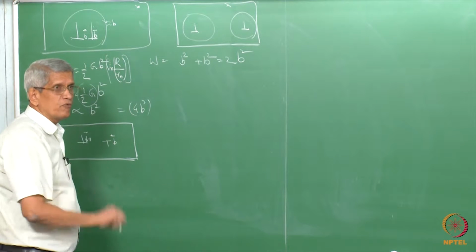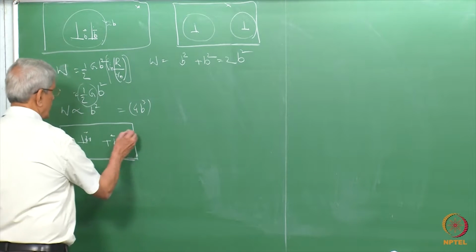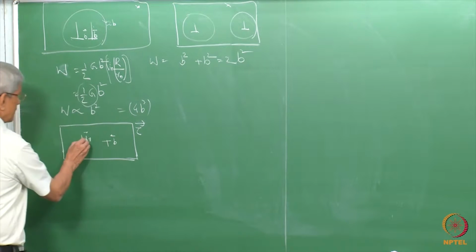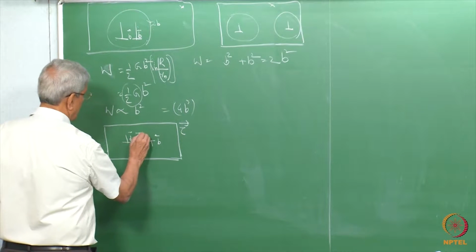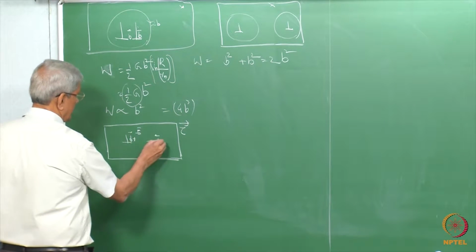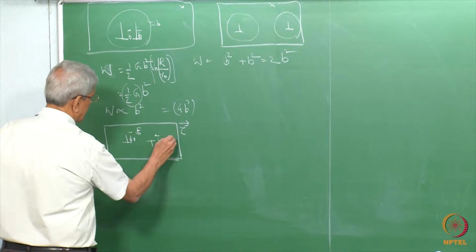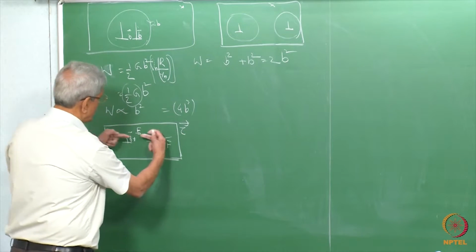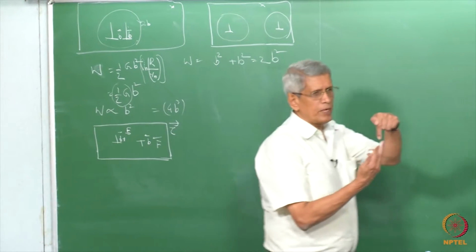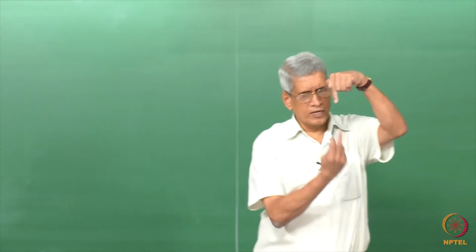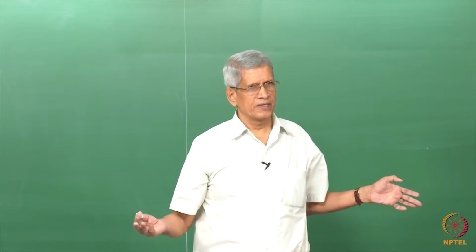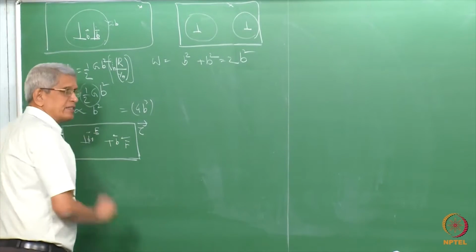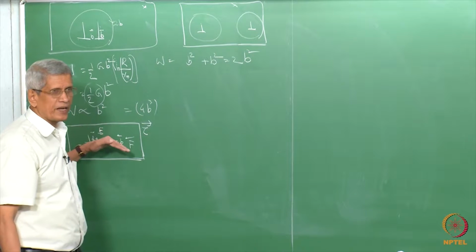If we use the force equation which we have written earlier, and apply a stress in this direction, in one dislocation the force will act in this direction, and in the other the force will act in the opposite direction. So this dislocation will move in this direction and that dislocation in the other. When they meet, the extra planes will become one on top of the other and the dislocation will vanish. That means these dislocations are going to attract each other. Qualitatively we can understand that.